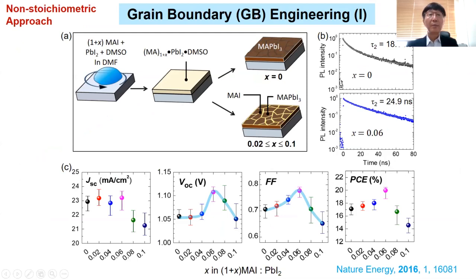For instance, for grain boundary engineering, we add some additional excess materials in the precursor solution. Then this additional excess precursor material can sit on the grain boundary and passivate the grain boundary. Therefore, you can increase the open circuit voltage and fill factor. There is no significant change in short circuit photocurrent density at a given composition.